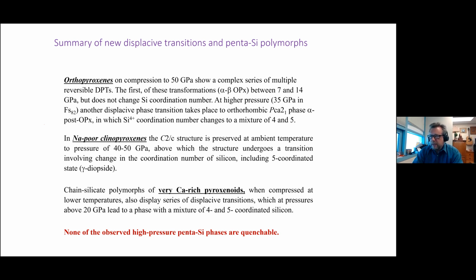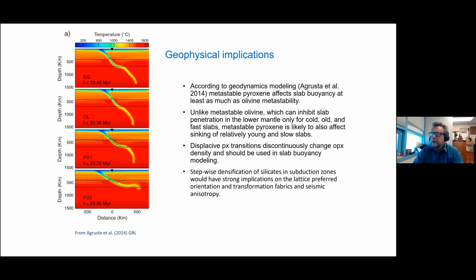None of the observed high pressure penta-coordinated phases in this particular system are quenchable, so they do not provide us with the opportunity to use other spectroscopic techniques that have to be performed at ambient pressures to examine these unusual hypervalent polymers. In terms of implications, the possibility of preserving pyroxenes beyond their stability field has been explored by Agrusta in a couple of papers. And he concluded that such preservation in cold subduction zones can indeed contribute to controlling whether the subducting slab is going to stagnate or penetrate into the lower mantle.